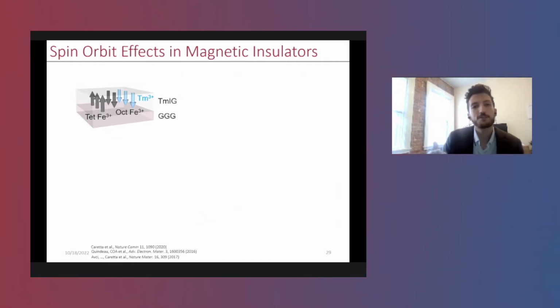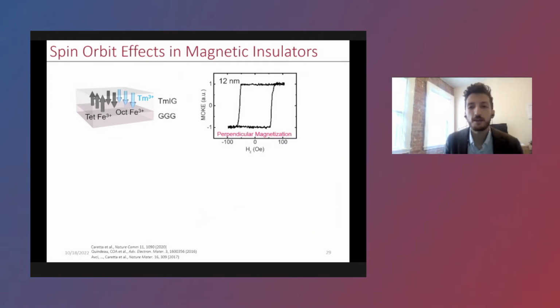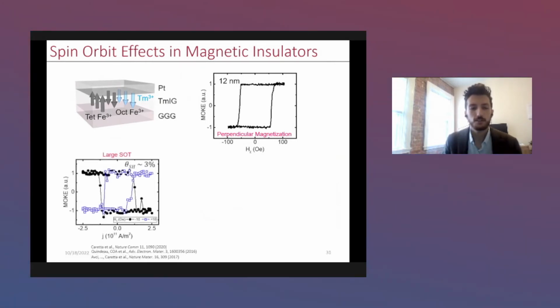So why is it that we're interested in them now? Well, really, one of the main reasons that we're interested is because we can grow them in very high quality with very thin thicknesses. And by thin, I mean just 1 or 2 unit cells while retaining a lot of the bulk properties, like the bulk magnetization. And so this allows us to really use interface effects to drive or dictate magnetic properties. So for example, we can use magnetostriction from lattice mismatch with substrates using epitaxy to induce perpendicular magnetization in these materials. You can also use torques that are driven across these interfaces to induce magnetic switching, which has been shown earlier in this session as well, using just currents.